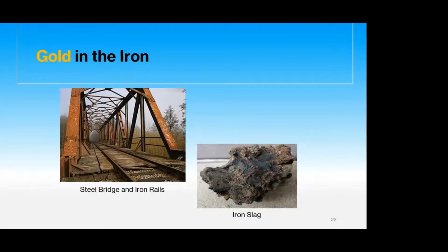Geological Survey at nearby Hopewell Furnace found that most of the copper and gold in the ore became incorporated into the cast iron. A smaller portion ended up in slag produced by the furnaces. If the gold suffered a similar fate at Cornwall, as would be expected, then most of it is distributed around the United States and the world in iron and steel that originated at Cornwall and the other furnaces that were supported by the Cornwall ores. And a lesser amount resides in the slag produced at Cornwall and the other furnaces that used Cornwall ore throughout the 18th, 19th, and early 20th centuries.